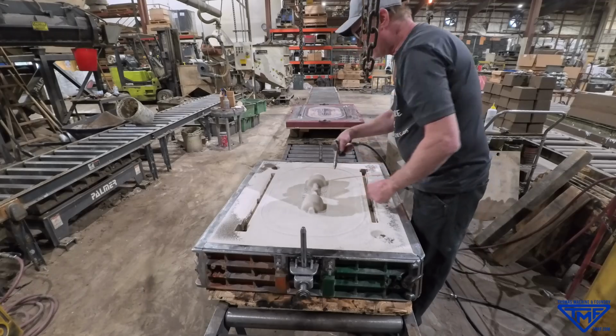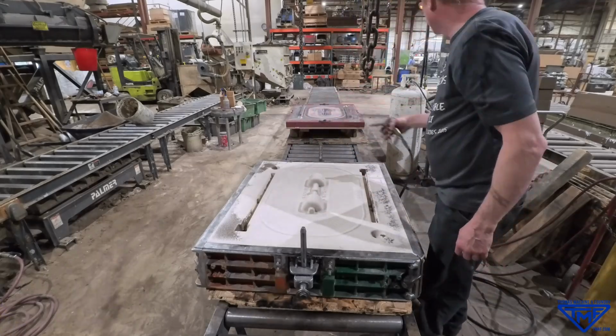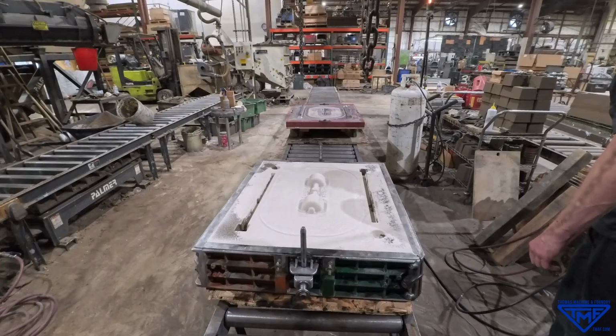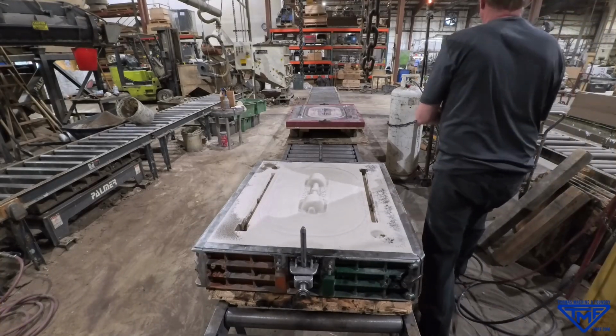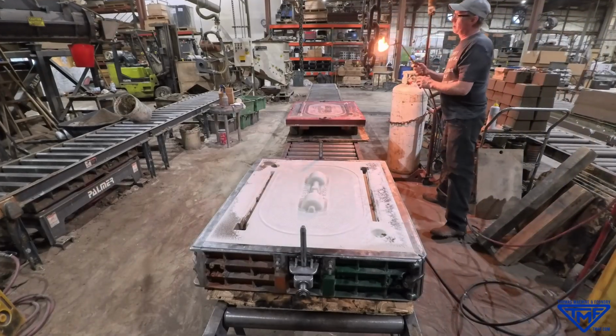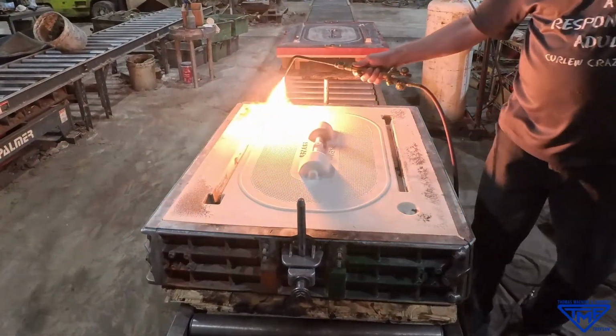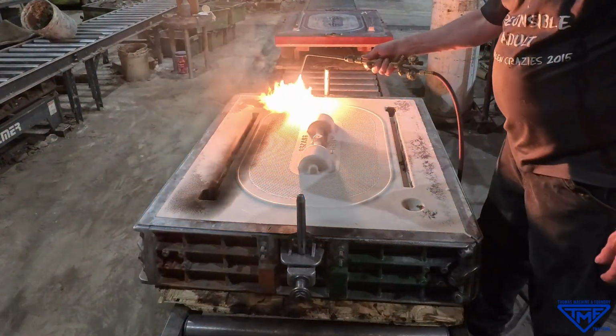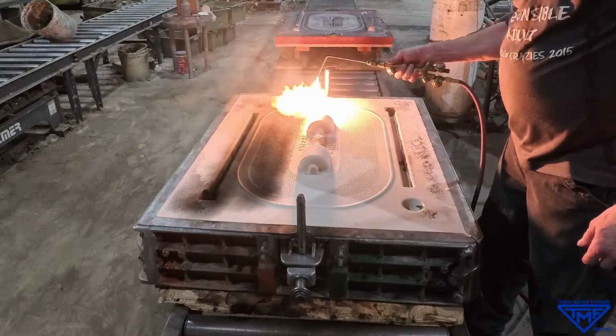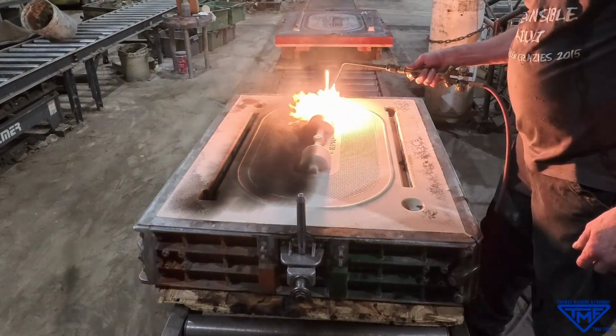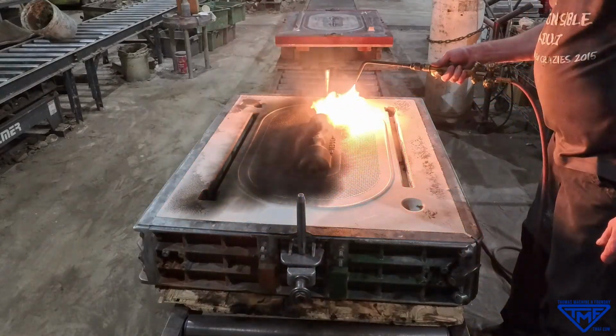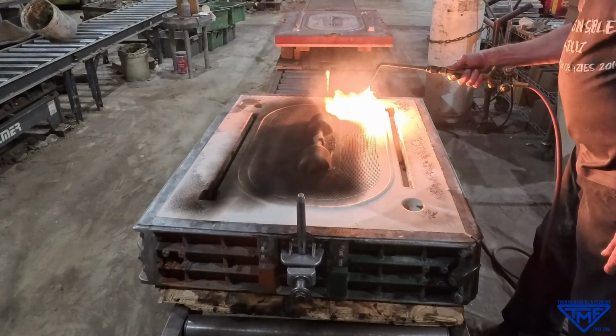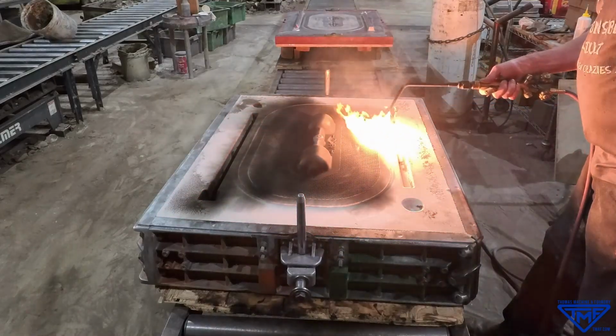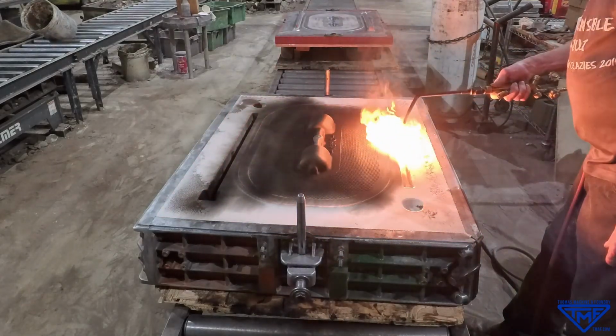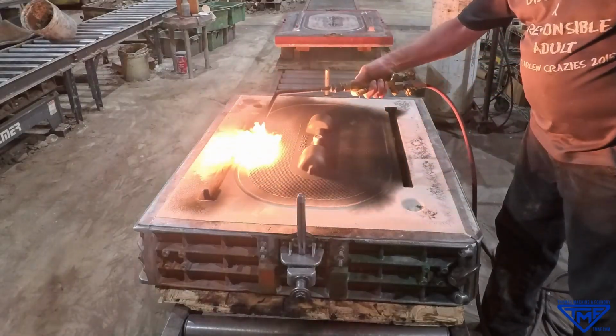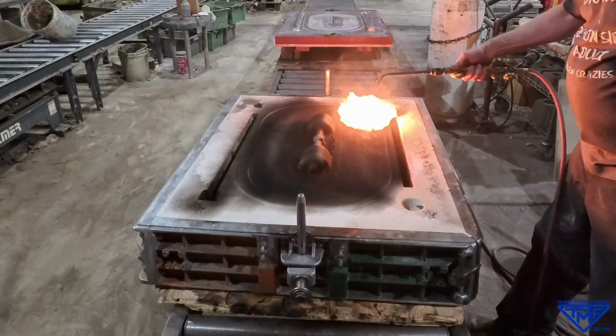Randy inspects the mold surface for loose material or imperfections before using an acetylene torch to smoke the mold. Smoking applies a thin layer of carbon to the mold surface, helping the aluminum flow more smoothly and further improving the final surface finish of the casting. This also helps prevent defects, such as cold shuts or incomplete fills.